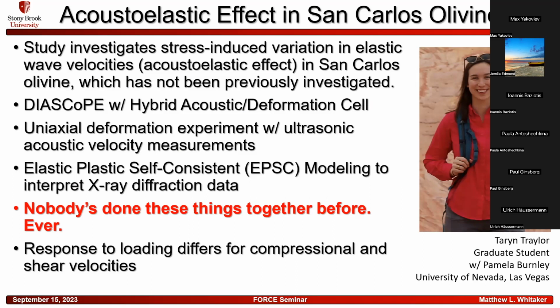So this uses the DIASCoPE system with a hybrid acoustic and deformation cell assembly. And there's a uniaxial deformation experiment with ultrasonic acoustic velocity measurements combined with elastic plastic self-consistent modeling to interpret the X-ray diffraction data. And no one has done this outside of Taryn before. So this is a completely new field that she's walking into, and she's killing it, if I can say so myself. The response to loading definitely differs for compressional and shear wave velocities.